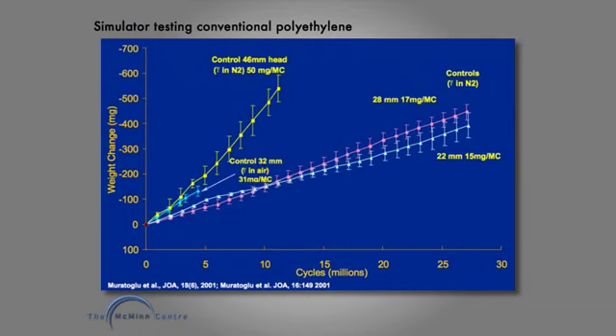The lowest wear is with a 22 millimeter head, followed by the pink, which is a 28 millimeter head, and the blue, which is a 32 millimeter head, and the yellow, which is a 46 millimeter head. The bigger the head size against conventional polyethylene, the bigger the wear volume of polyethylene. And so osteolysis and other wear debris associated problems were greater with a bigger head size.